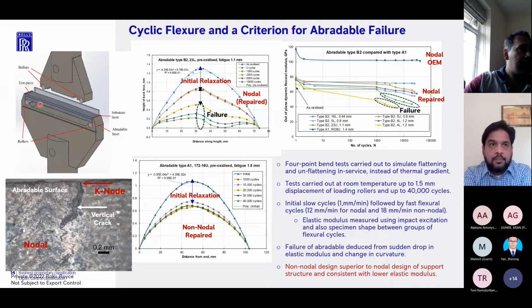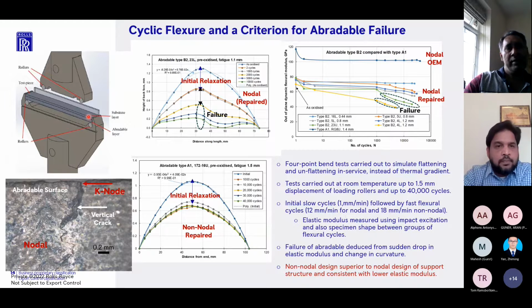Typically we had a test piece where the abradable was sitting. We applied a load under 4-point bending. The 4-point loading rollers apply a load on the upper surface, causing the specimen to flatten and unflatten as the load is applied and then removed. We did a series of tests on the nodal and the non-nodal design. We typically applied increasing displacements at the loading rollers, going from 0 to about 1.5 millimeters and up to about 40,000 cycles. You can keep doing this to higher and higher numbers of cycles, but for the tests that we did, we got the response that we needed after 40,000 cycles.